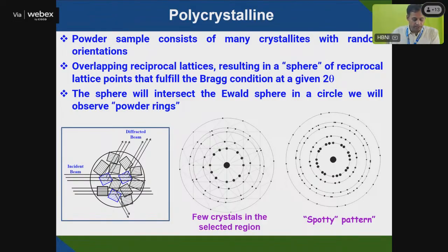But if you take a polycrystalline material, in a chunk of sample you can see there are many planes. Some black planes are there, some blue planes are there. If the incident beam falls on the blue plane, it will be oriented in one direction. Planes like the black plane will be oriented in another direction. So corresponding to the blue plane, you will get one dot for one plane.